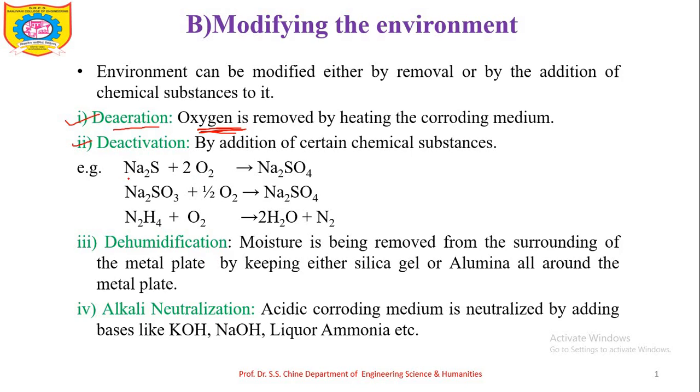How? Suppose you add sodium sulfide. Then this sodium sulfide will react with this oxygen to form sodium sulfate. Or hydrazine also reacts with the oxygen to form H2O and N2. So what happens? This oxygen which is free and leads to the corrosion will get combined with another molecule. Now it is not free for the corrosion. Okay. So in this way deactivation can be done.